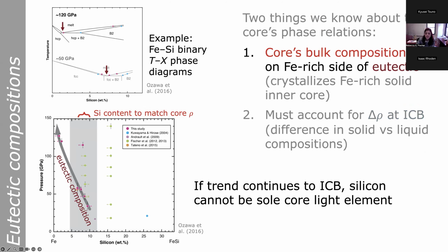Okay, so to start with this first constraint, we have to be on the iron-rich side of the eutectic. This is an example coming from the iron silicon system from a study by Ozawa et al. 2016. So again, this is a temperature composition phase diagram, like the schematic one I just showed, only this one's based on actual data. And these red arrows point out the eutectic composition. So there it is at 50 GPa. By 120 GPa, it has shifted to lower silicon content.